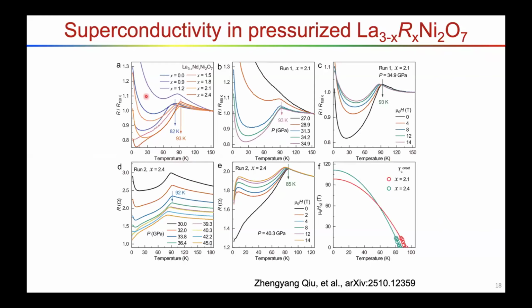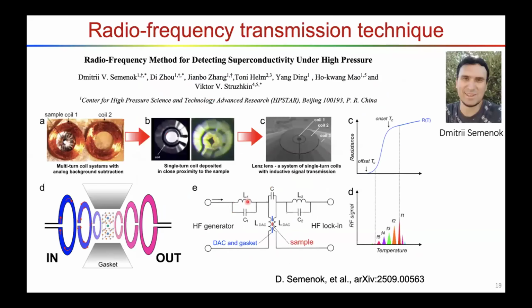When we measure the superconductivity under high pressure, we found that the TC is enhanced to around 93 Kelvin. So they are for different compounds and different pressures. Our collaborator, Dimitri Semenok, used another technique, the so-called radio frequency transmission technique, to measure superconductivity under high pressure. They have successfully used this technique to measure superconductivity for hydrogen-rich materials under extremely high pressure. There's a paper on arXiv, so I will not go into details on the technique. But